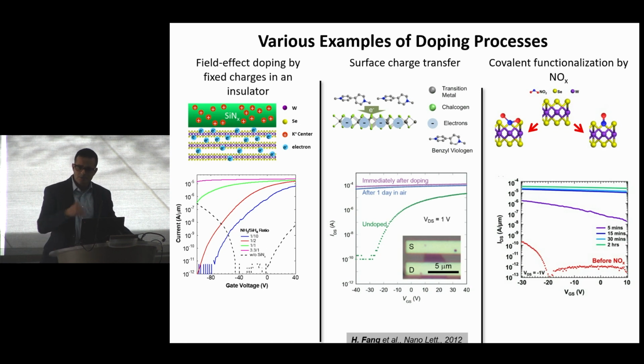Now, there are problems with this. Nitrides, the fixed charge density does not linearly scale with the thickness of the nitride. You need a minimum thickness before you start to see some of these effects. And so it may not be very scalable, but you can use materials like aluminum oxide, which are well established to also have fixed charges.